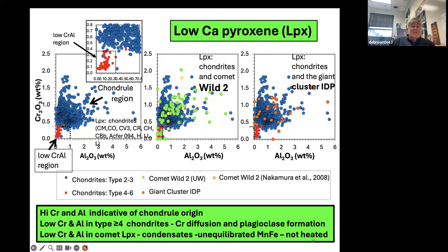Now in chondrites, there's these red points on the lower left of the left-hand plot, which are low because of heating, because of parent body heating. Chromium has diffused out of low calcium pyroxene, and aluminum has gone out because it's formed plagioclase. We see this similar pattern in the comet, but we think it's for different reasons. It's not due to heating. These are actually condensates, and because the unequilibrated manganese, iron, and other factors indicate that these samples were not heated, like the high metamorphic grade chondrites.